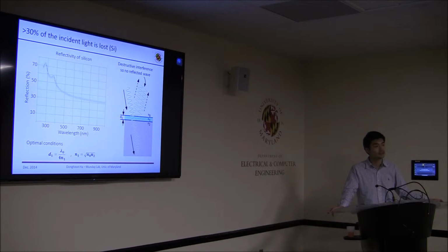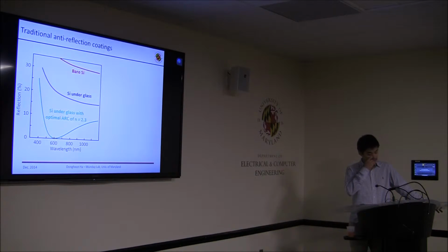And how can we do that? Simply, we can add thin film dielectric layers on top of the solar cells. And by adjusting the thickness and the refractive index of that layer, we can minimize that amount. The bottom shows the optimal conditions for that. And this figure shows the effect of the traditional anti-reflection coatings. Red is the reflectivity of bare silicon, which is one of the most popular materials for solar cells. And that is even greater than 30%.